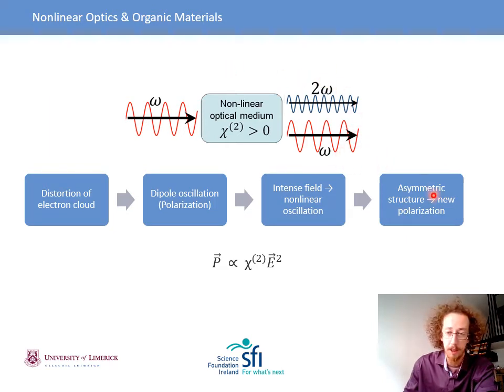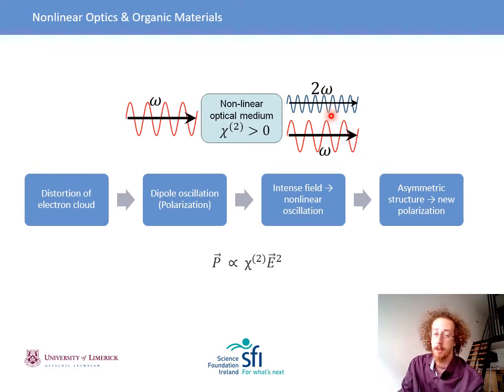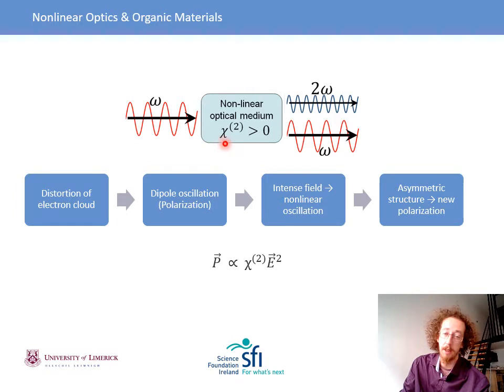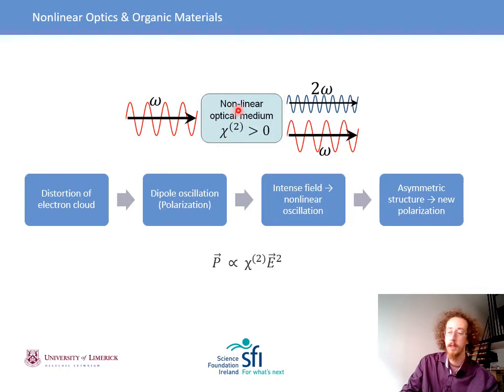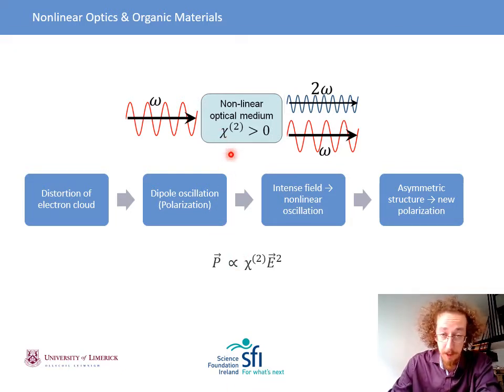The simplest example of this is called second harmonic generation, where you convert the incident wavelength into a new polarization that has half the wavelength, or twice the frequency. The efficiency of this process is governed by the material property chi-2, or the non-linear susceptibility tensor, in the second order. So it's about finding this property and the effect of morphology on it.